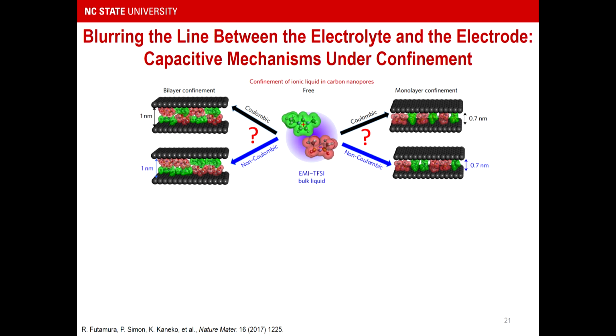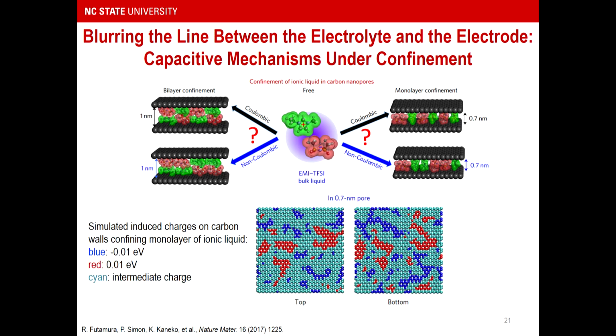We're asking the question of where to draw the electrochemical interface, and so these are examples of ionic liquids that are confined between layers of carbons, forming what are called non-Coulombic interactions, meaning that they're actually pairing up with ions of same charge, something that would typically be very, very energetically unfavorable in the bulk. And when you simulate the induced charges on the carbon walls, you see that it's not homogeneous. There's actually regions where charge appears to be highly localized. So everything changes when you're looking at mechanisms under confinement.